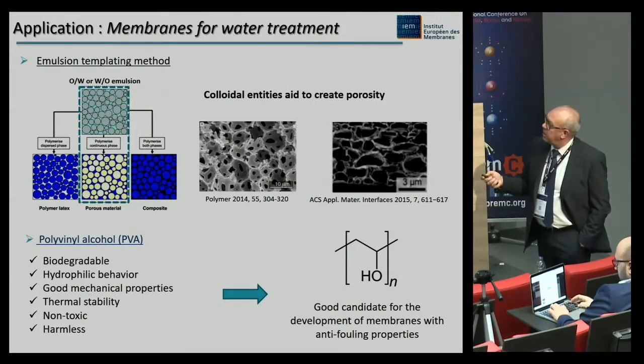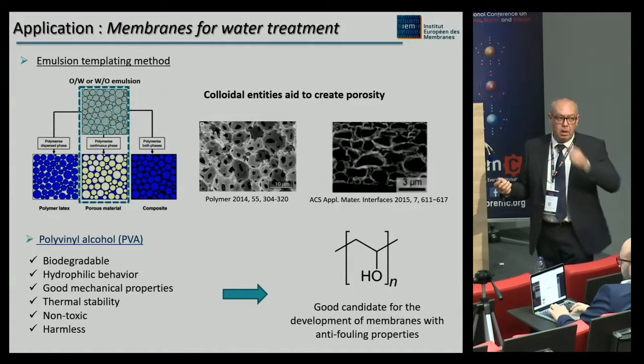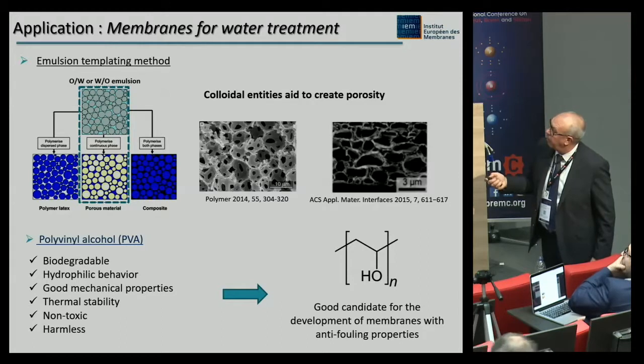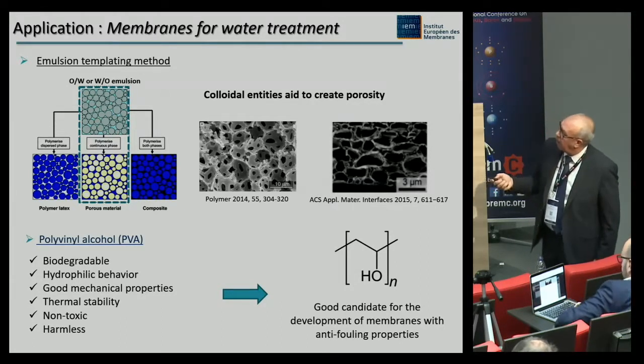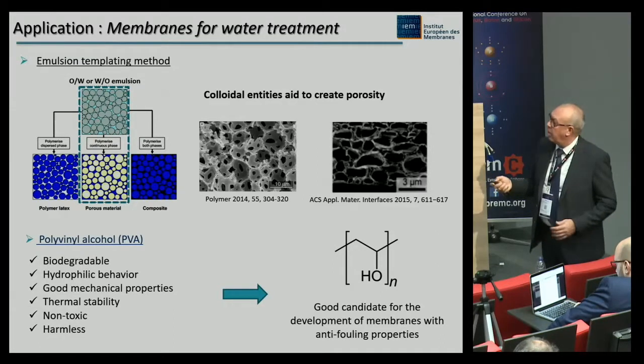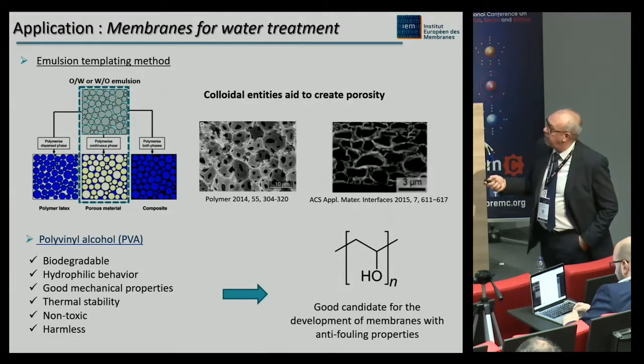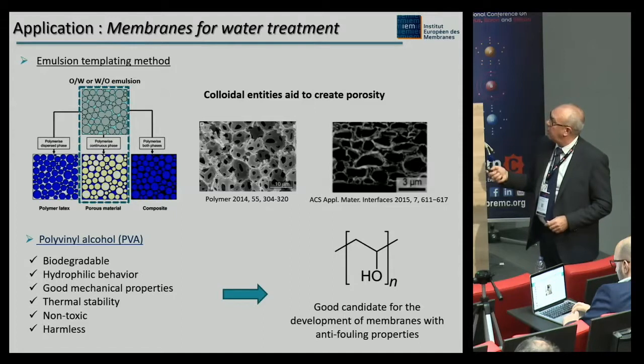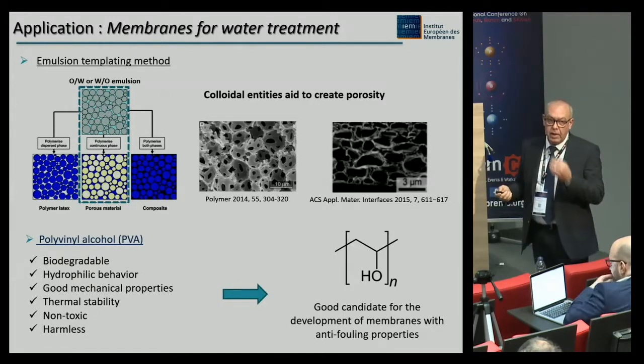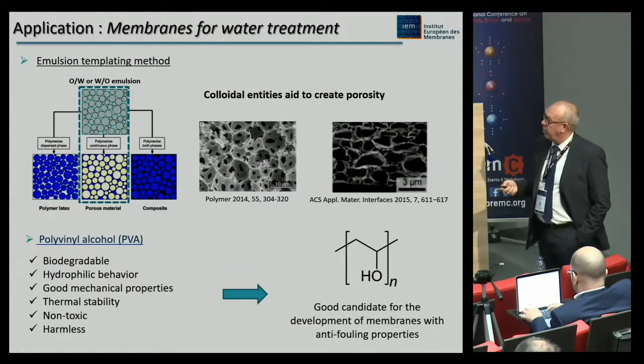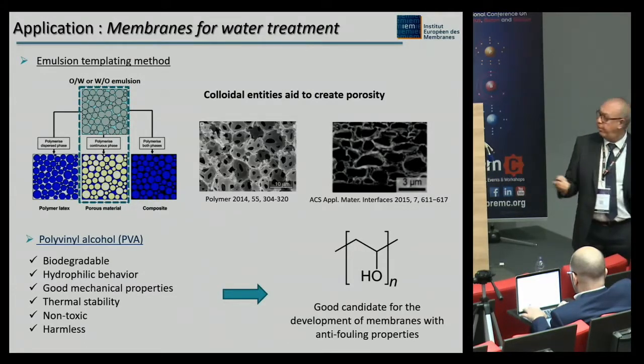If you look at this scheme, you can see what is possible to do with these emulsions. If you polymerize both phases, you obtain a composite. If you polymerize only the dispersed phase, you can obtain a polymer latex. And if you polymerize the continuous phase, you obtain a porous material. This is quite evident, as this has been done in these two examples. In our case, we have used polyvinyl alcohol to prepare membranes, because it is biodegradable, it displays hydrophilic behavior, good mechanical properties, and is particularly non-toxic and harmless. So it's a good candidate for the development of membranes with anti-fouling properties. The idea is to use these membranes for water purification.